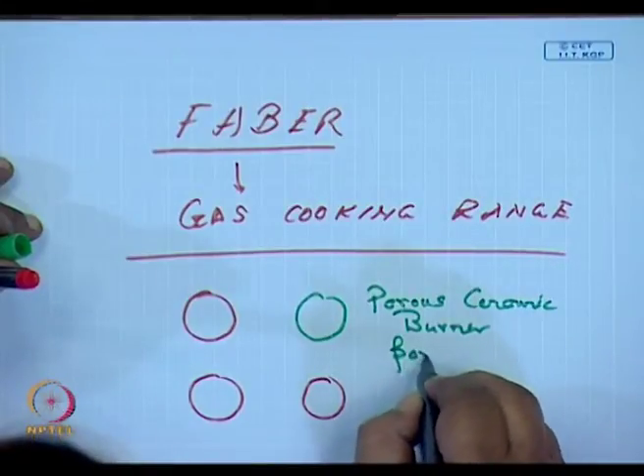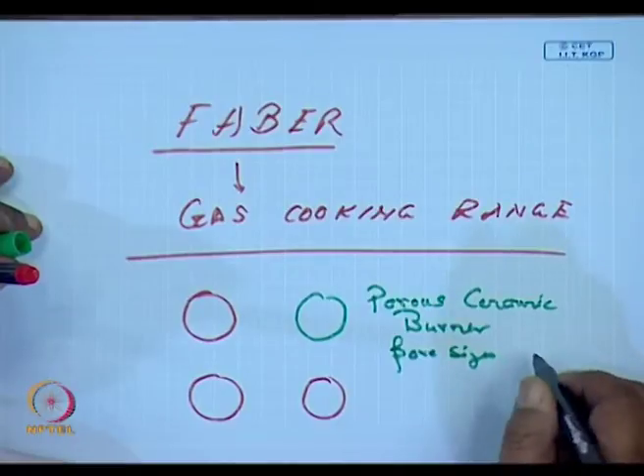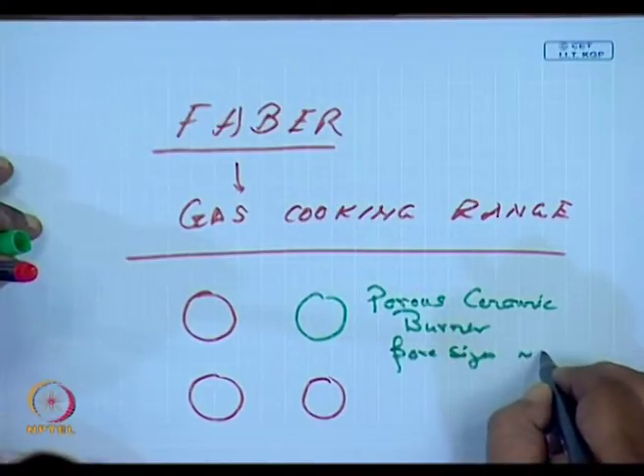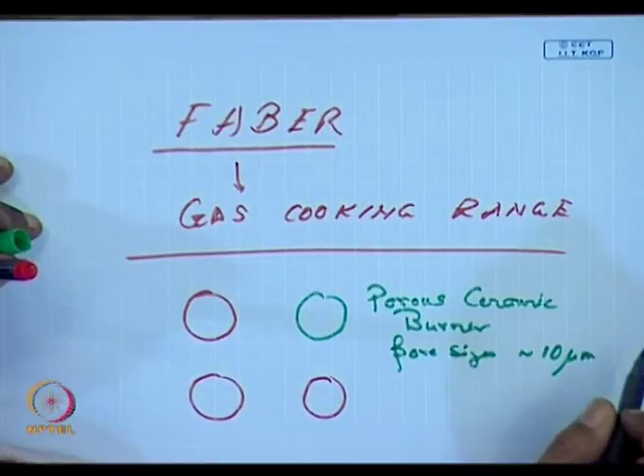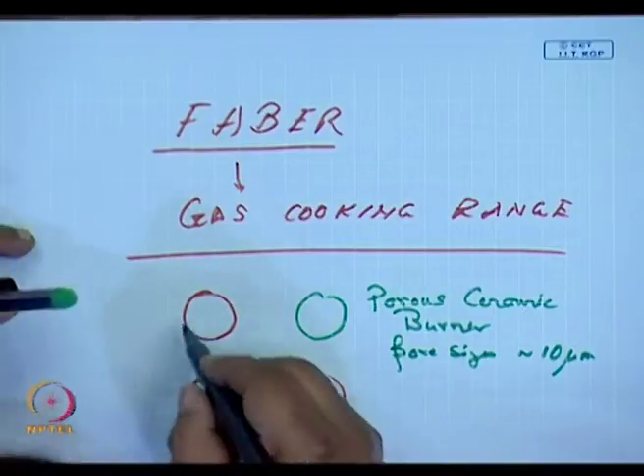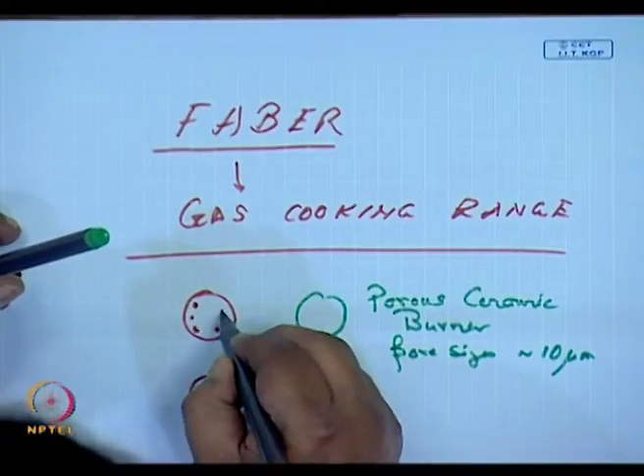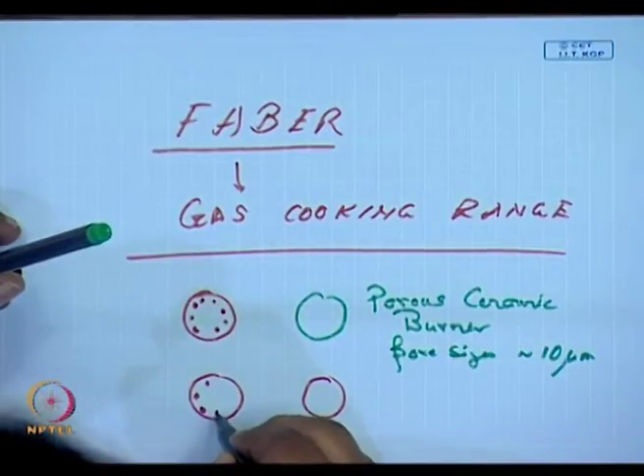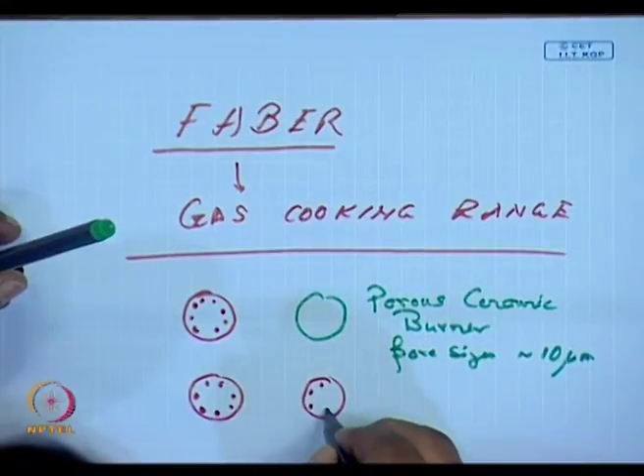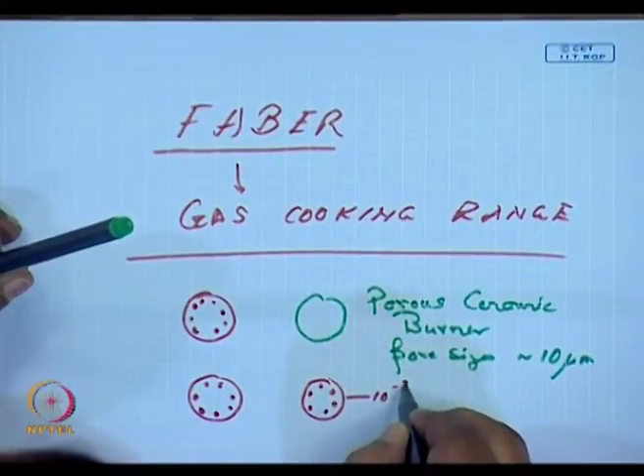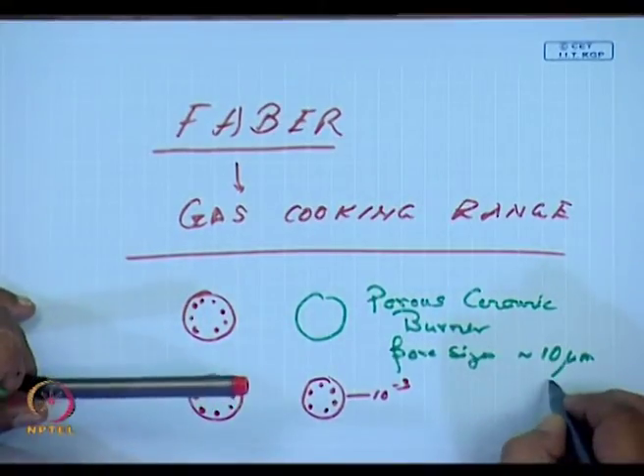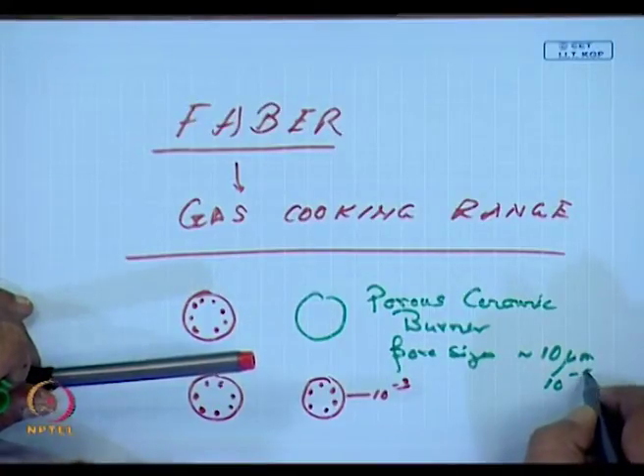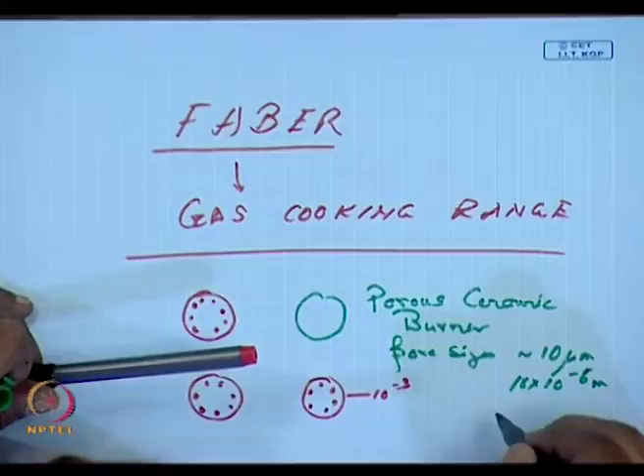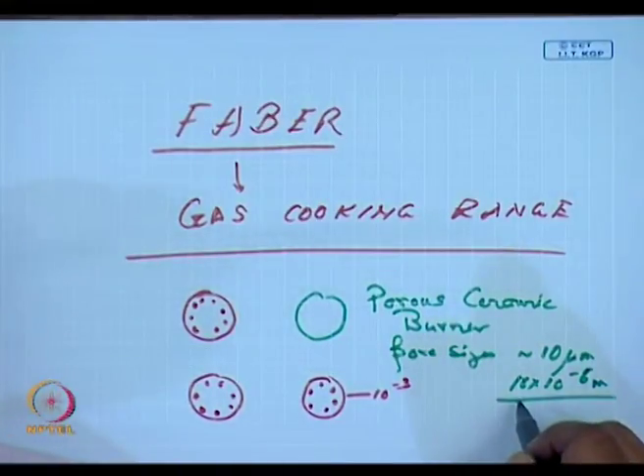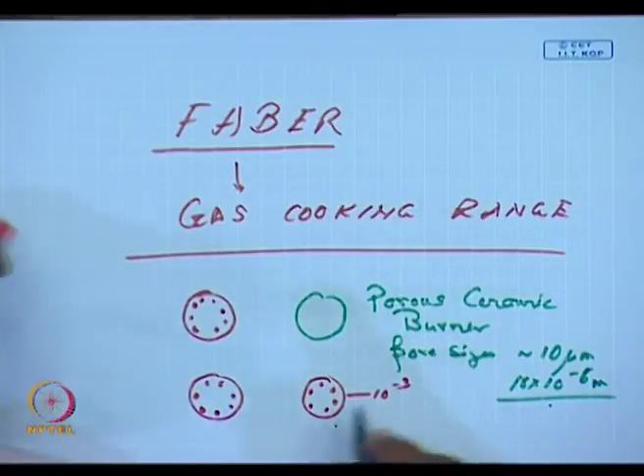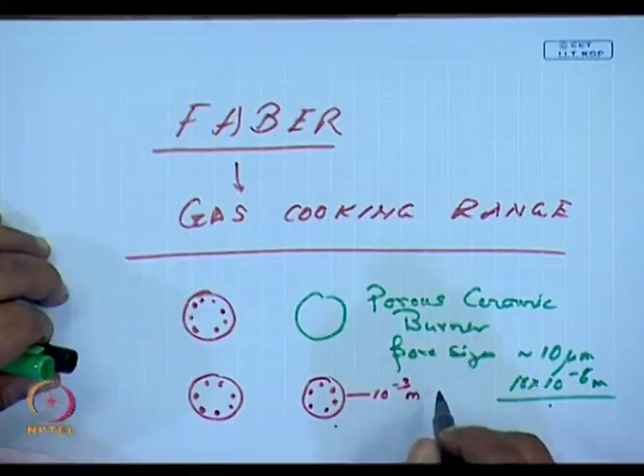Pore sizes in the porous burner are of the order of 10 micrometers. And as I said, the conventional burners have holes, and these holes measure 10 to the power of minus 3 meters. Remember, 10 micrometers means 10 to the power of minus 5 meters. So in the porous burner, the pore size is that fine, while in the conventional ones, the hole size is 10 to the power of minus 3 meter, or 1 millimeter.